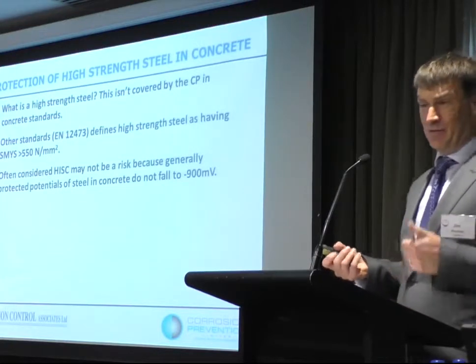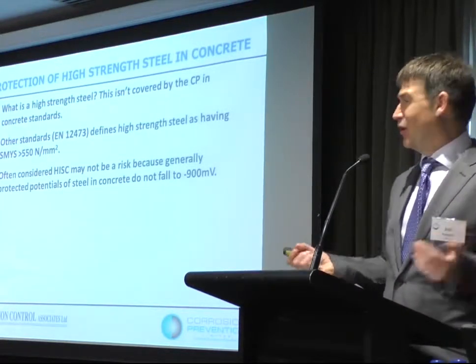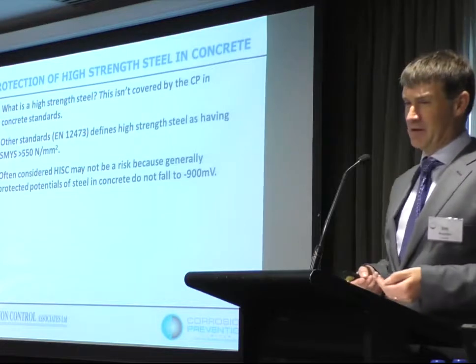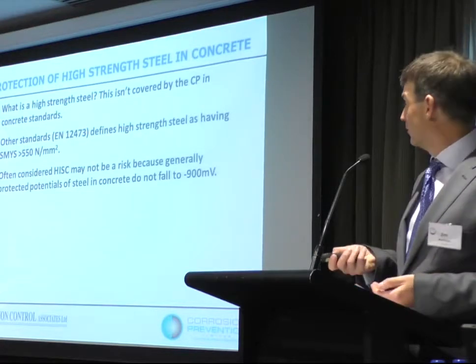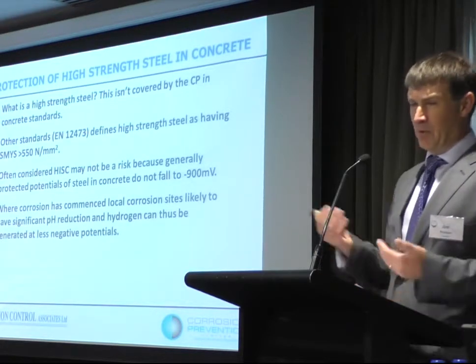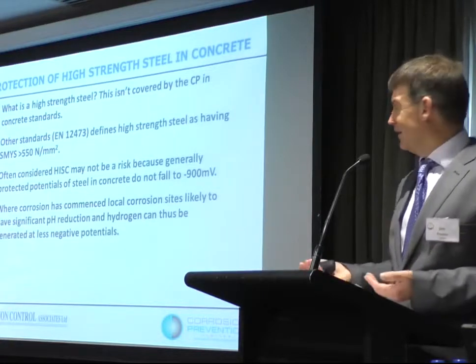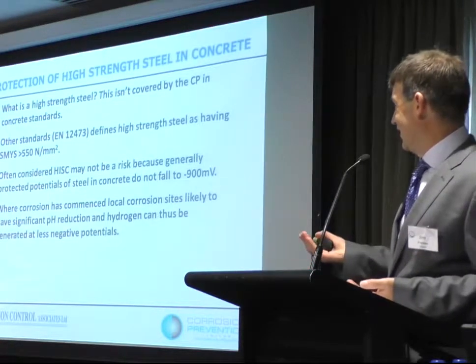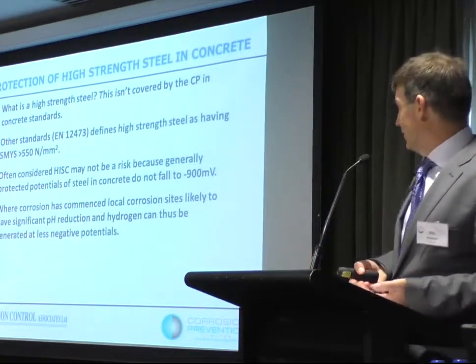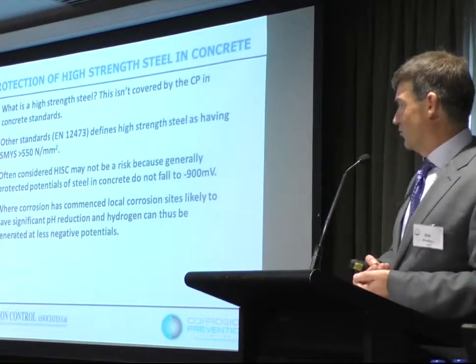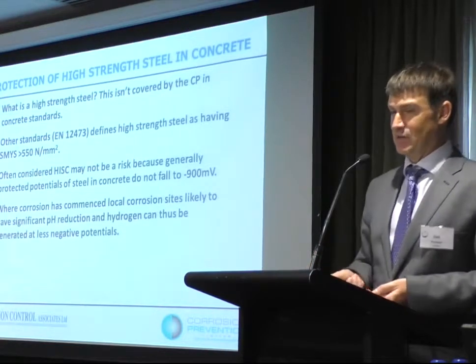It's often considered that if we're doing an atmospheric reinforced concrete structure, we're not going to get a potential more negative than minus 900, so maybe there isn't an issue. But we know that if corrosion is initiated, at those corrosion sites the pH might be a lot less. So do we have an issue that we can generate hydrogen in those cases at less negative potentials?